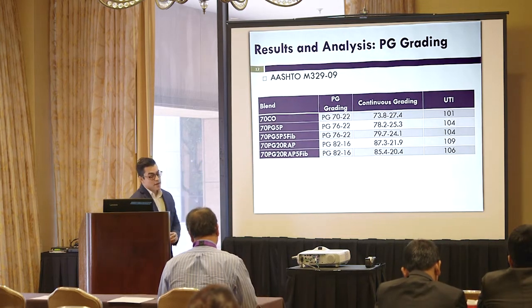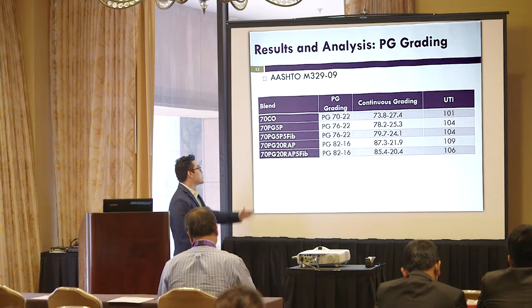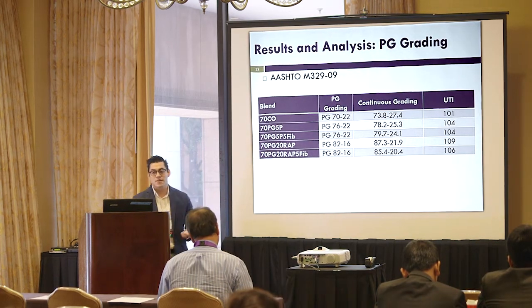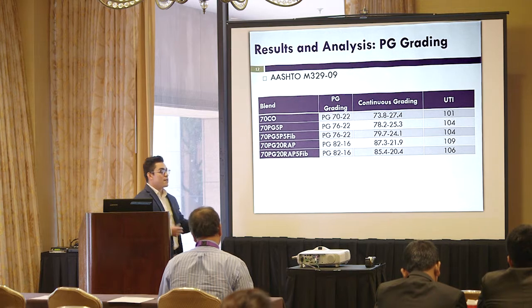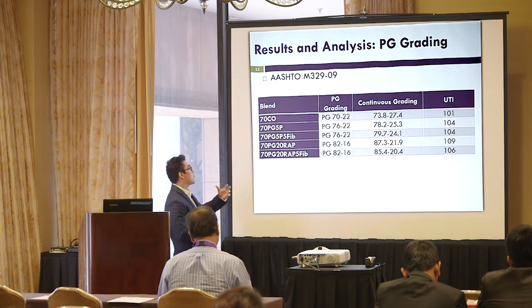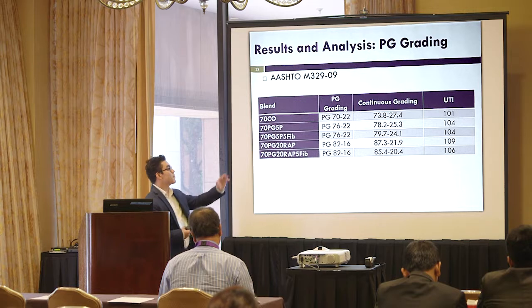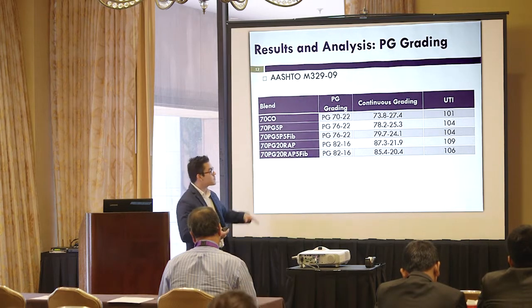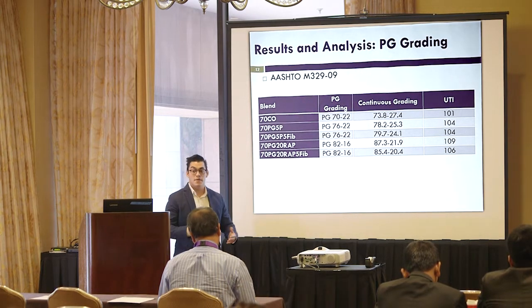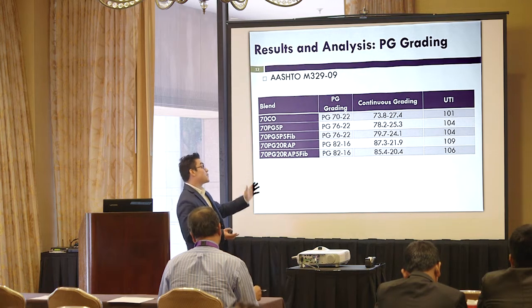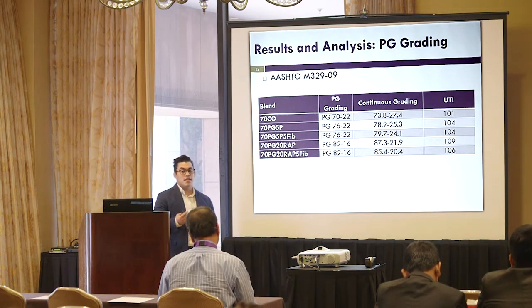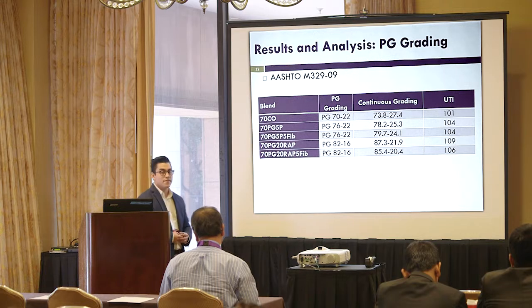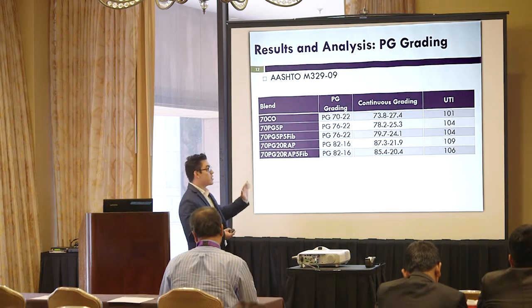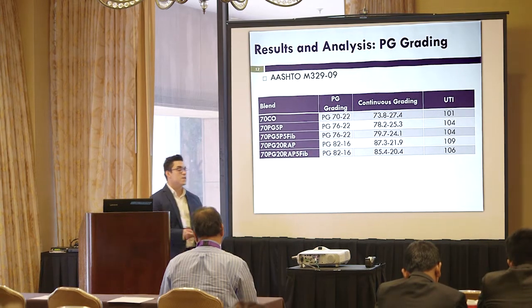So for the PG grading results, as we were expecting whenever we were adding recycled materials, the high temperature of the PG grading increased from 70 to 76 with the RAS, and from 70 to 82 with the RAP. And also we observed that the addition of these fibers didn't have any effect on the PG grading, or on the UTI.